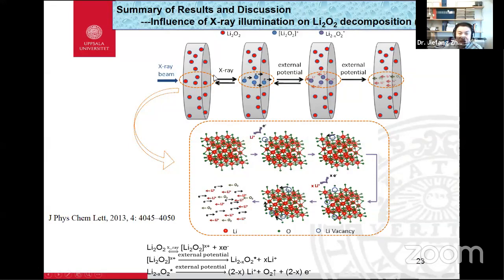So during the X-ray irradiation, the X-ray can kick out the electron from the lithium peroxide. Then the intermediate can release the lithium ions for the decomposition. Without the external circuit, the electron will recombine with the intermediate back to the lithium peroxide. That's why the electrochemical condition is very important in this case. So it's not the pure X-ray damage.